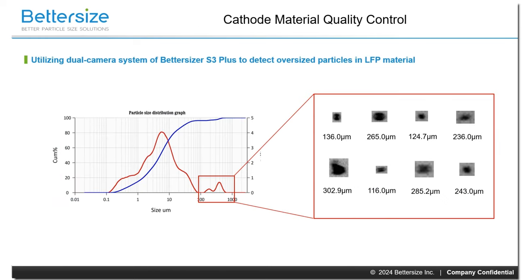Here is another example of using Bettersizer S3+ to help evaluate the quality of particles. But this time, we are making measurements of processing LFP materials. The LFP materials are also insoluble in water, but the size distribution of LFP particles varies according to their preparation process, such as this sample we measured in the Bettersizer lab. The particle size distribution curve shows a bimodal dispersion, which means the sample includes 2 groups of particles of different sizes. Thanks to the image analysis part of Bettersizer S3+, we can easily find out what are the larger volume particles which cause the actual peak on the PSD curve.